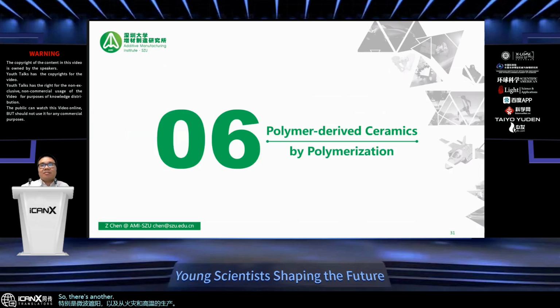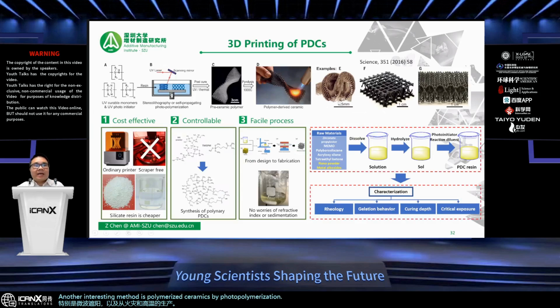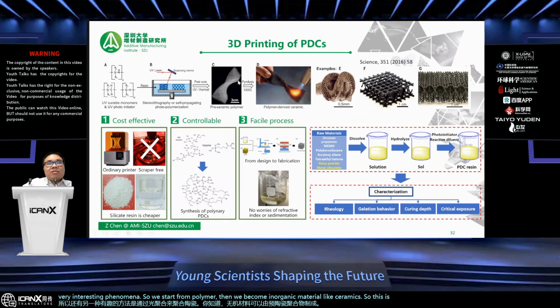Another interesting method is polymer-derived ceramics by photopolymerization. The inorganic material can be fabricated from a pre-ceramic polymer. That's a very interesting phenomenon. So we start from a polymer, then it becomes an inorganic material like ceramics. This was published already in 2015 by the Lawrence Livermore U.S. National Laboratory, and they used a UV-curable photo ceramic polymer, then used photopolymerization 3D printing to get the green parts. Then at high temperature, 1000 degrees C pyrolysis, we can get the polymer-derived ceramics.